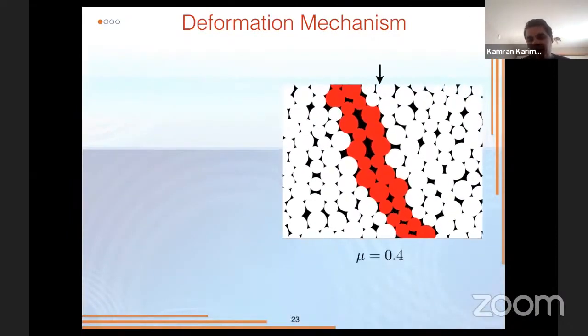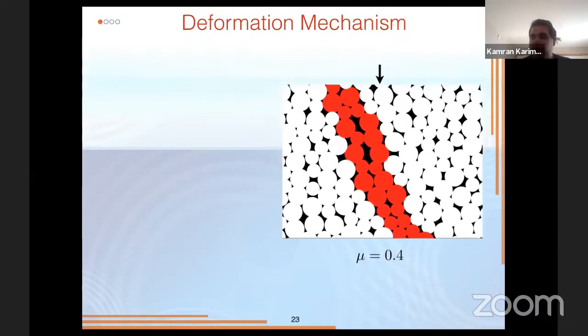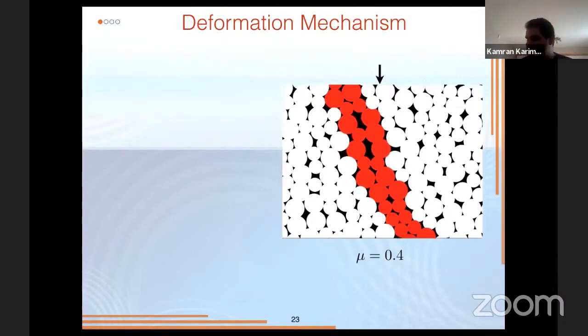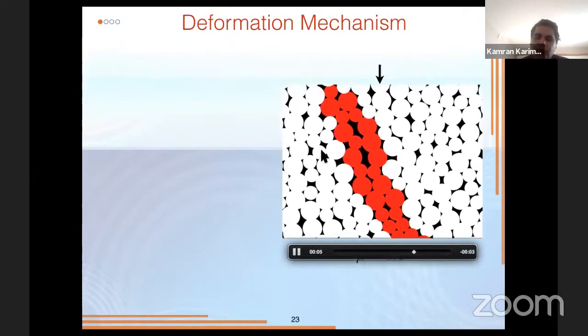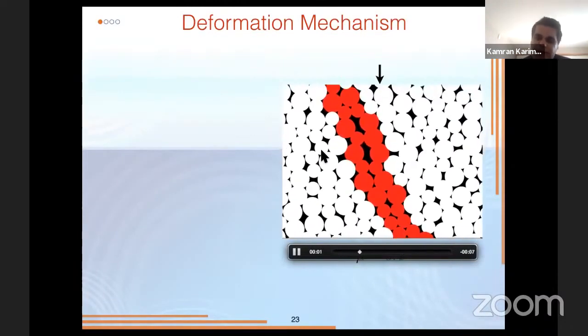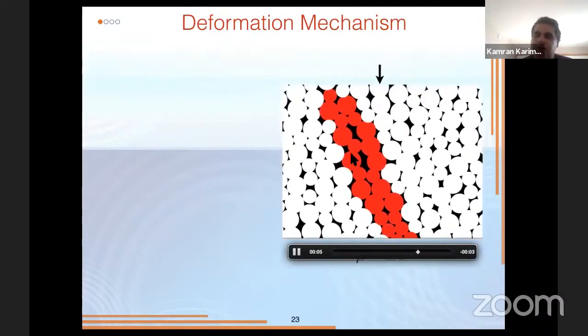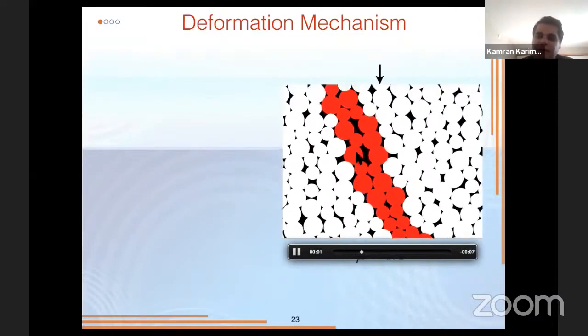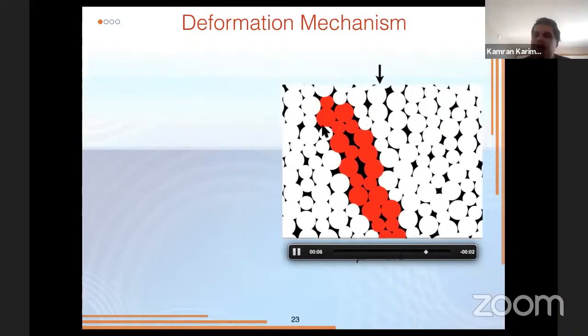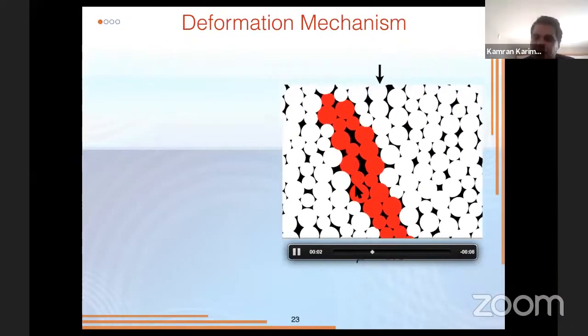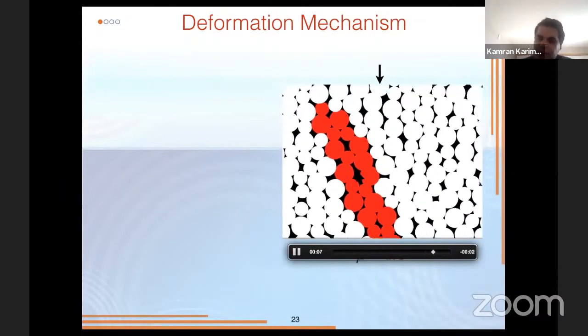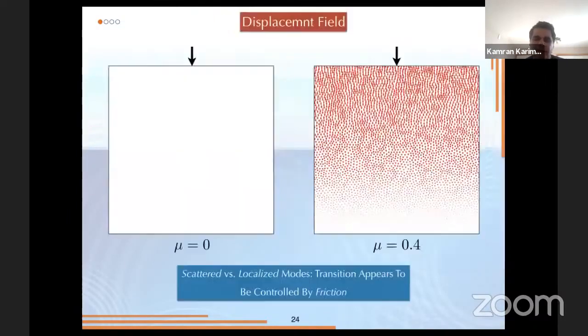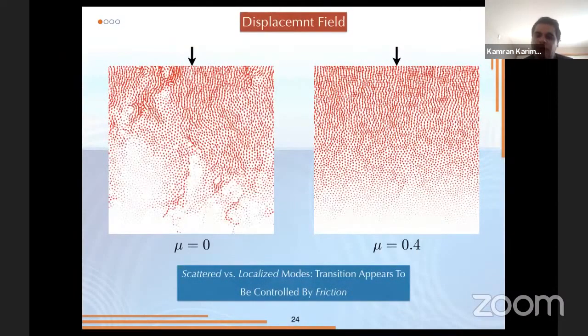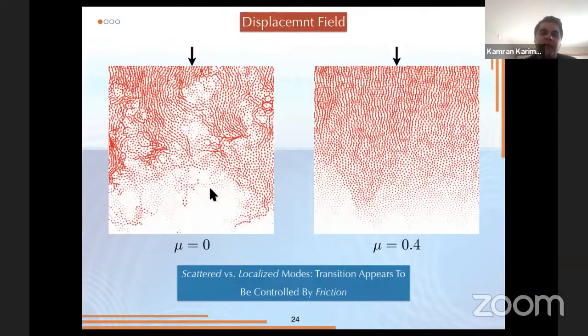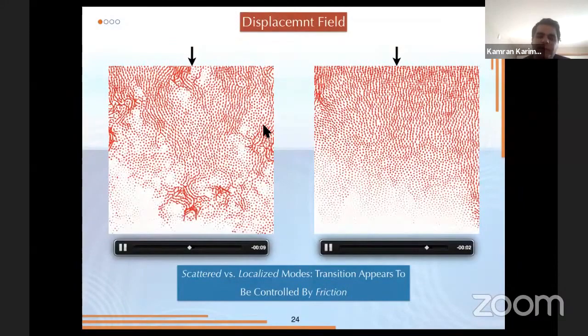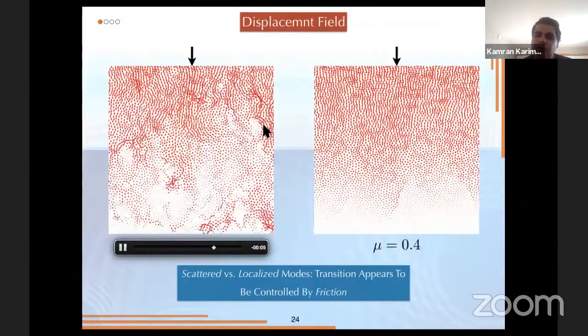This was for frictionless disks, and we can play the same game for the frictional case. Here you can see two large blocks slide past each other, and you can see significant dilation, due to the roughness of the surface and the polydispersity of the particles. So we get two really different elementary deformation mechanisms associated with frictionless and frictional particles. Here I'm showing these transformation zones at the sample size level.